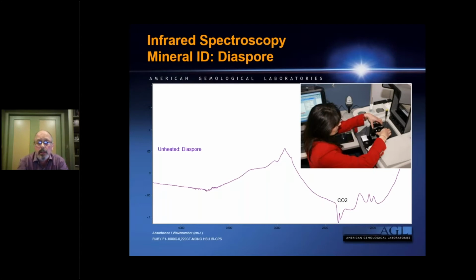We also use things like spectroscopy. Infrared spectroscopy was something that I discovered in the early 90s: that actually we could identify foreign minerals occurring inside corundum through mid-infrared spectroscopy. So here, for example, is an inclusion of diaspore, and diaspore is an aluminum hydroxide mineral. You have others like boehmite, you have weathering minerals like kaolinite, goethite, gibbsite, and so on, that you can identify with mid-infrared spectroscopy. And these can help provide additional information because they alter, even at relatively lower temperatures. The presence of minerals such as this can help you ascertain that a stone is indeed unheated.